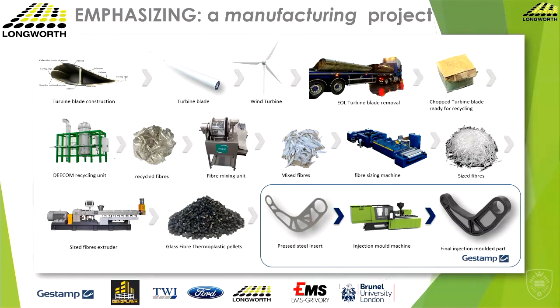From there, we've looked at various chemistries and sizing chemistries to make these glass fibres useful again, and I'll show you why you need to resize the material afterwards. Then, with Ford and Gestamp, we have put this into a Ford Camberlink structural part to show that we can actually use recycled feedstock. We can use the worst recycled feedstock to create a valuable material. So we can depolymerize the resin and create that valuable material.